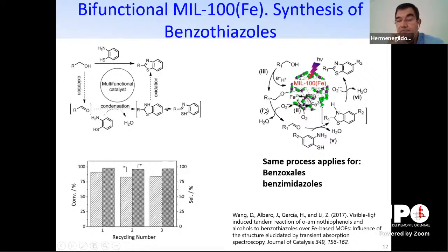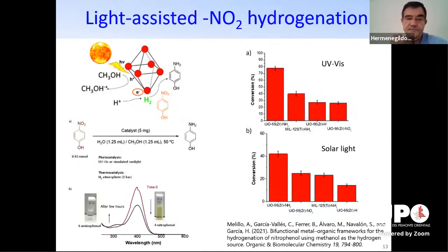So again, the reaction mechanism involves three steps. Of these three steps, two of them are oxidations. One of these oxidations is promoted photochemically, and the other requires acid catalysis. Well, this material is stable, and selectivity does not change upon reuse, and we have checked that there is no leaching of the metals to the solution.